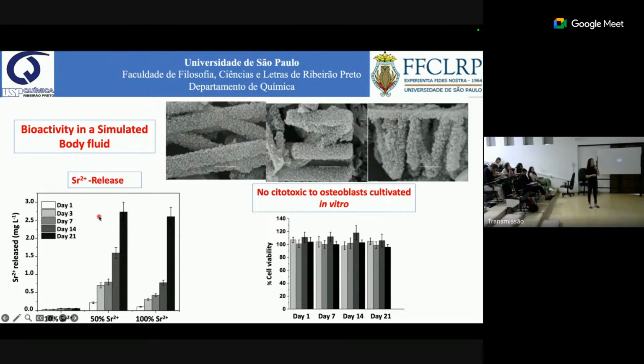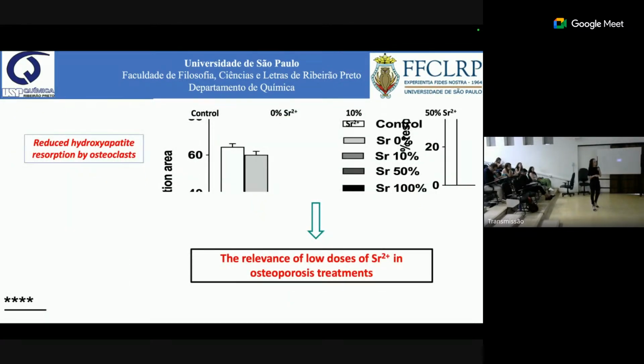These materials were able to deliver locally strontium, depending on the concentration of strontium we had in the nanotubes, and more importantly, in therapeutic doses to induce physiological mineralization and not pathological mineralization.